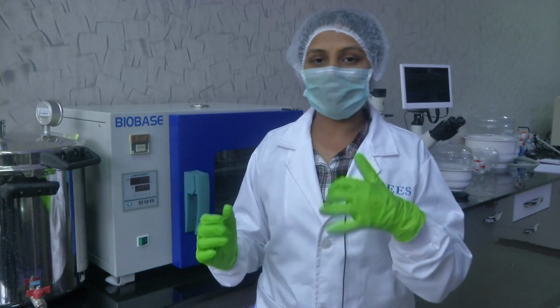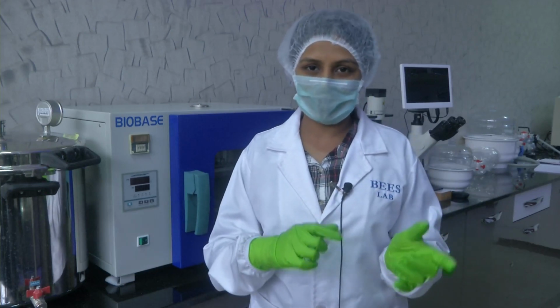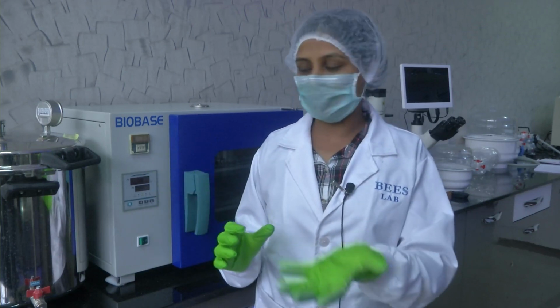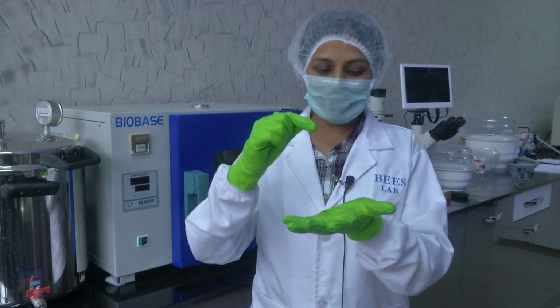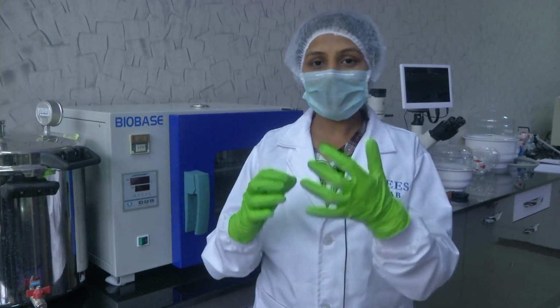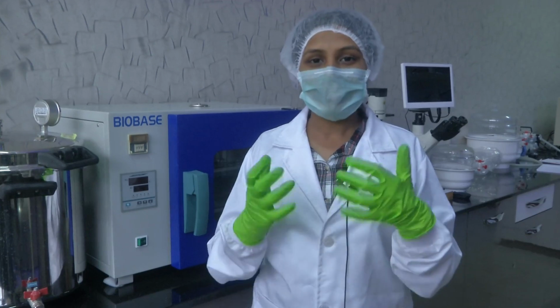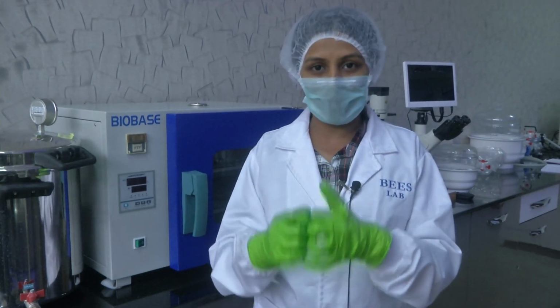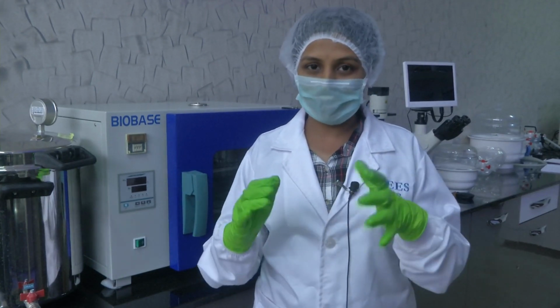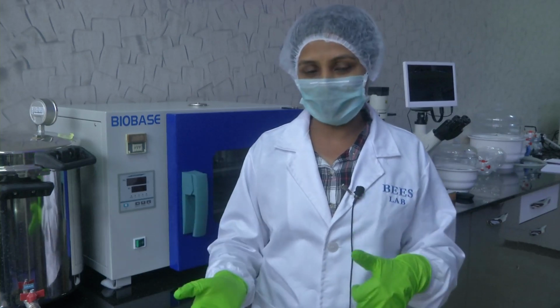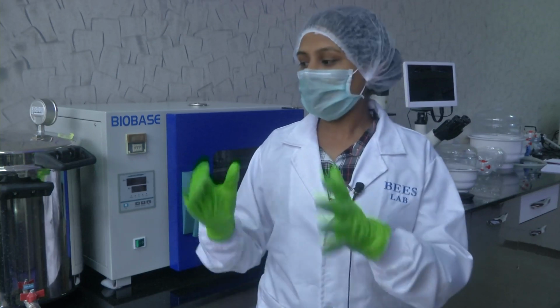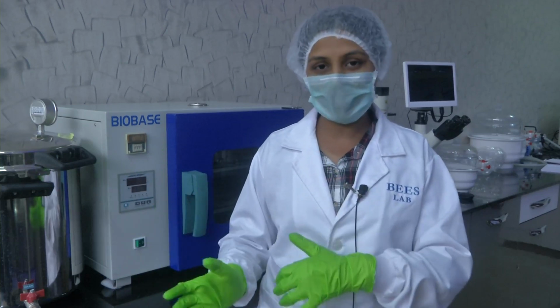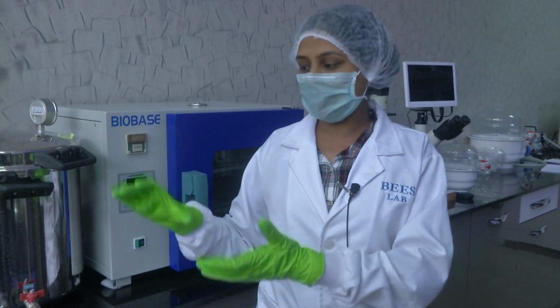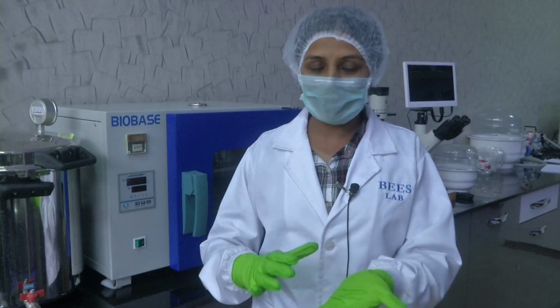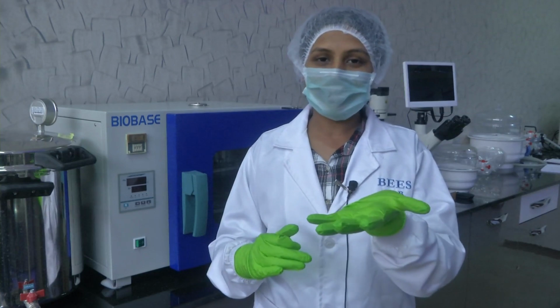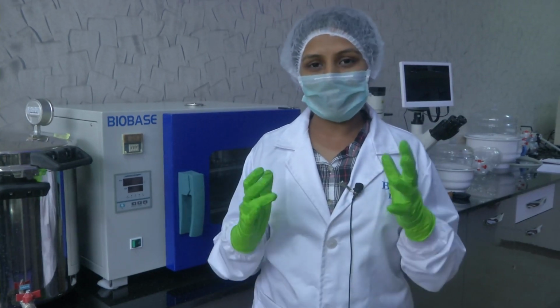Why is this step carried out and why is it important? Even before you put them into the developer solution, after exposure, you put the wafer onto your hot plate, and this ensures that for the part with the features which have to be developed, when you heat it, the chemical composition changes such that a highly efficient cross link is formed between the features which are to be formed, and the ones which are not exposed would be easily soluble in the developer solution. In order to ensure this process happens, you have to bake it after the UV exposure and set the desired temperature and time. And once you bake it, take it out, put it into your developer solution, and after developing, you would see the right, desired features on your wafer. So this becomes an important step.